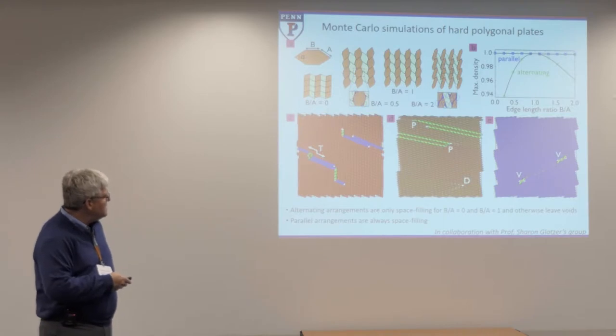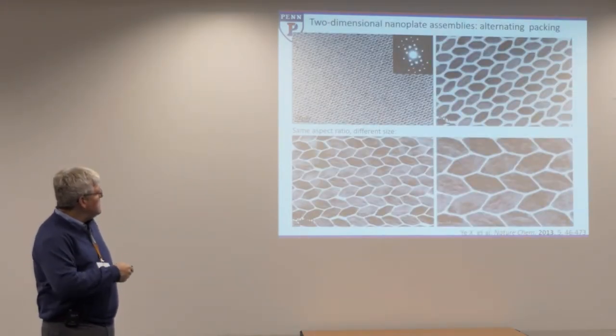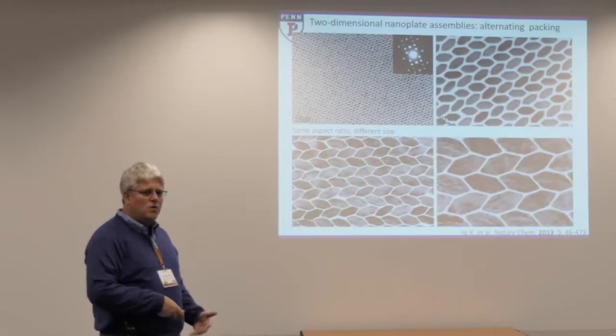So a lot of the packing motifs, maybe if I go back one. So when you think about the arrangement of these structures, simple close packing, or I should say, entropic effects, which generally push the system towards sort of a densest packing to optimize the energy of the system, don't explain these types of arrangements of the components. In order to get these particular types of architectures, you need some extra influence. And where we looked for this is in the realm of enthalpy. So basically the energy of, again, in chemistry terms, it's the bonding energy. It's the favorable, or in some cases unfavorable, interaction energy, and not just being at the mercy of trying to minimize the energy of the system.